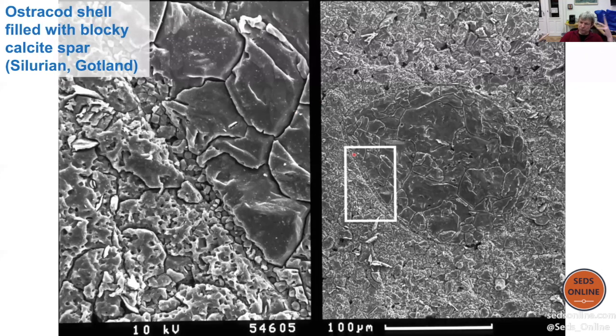And looking at another example, this is an ostracode shell here on the right-hand side. The shell is actually very thin. Here is a blow-up on the left-hand side. This is the shell. We see the pitted microspar crystals on the left-hand side, and we see normal calcite sparite here filling the ostracode. So in thin section, this would look like our grainy microspar, and this would be bright translucent, because it's just calcite spar.